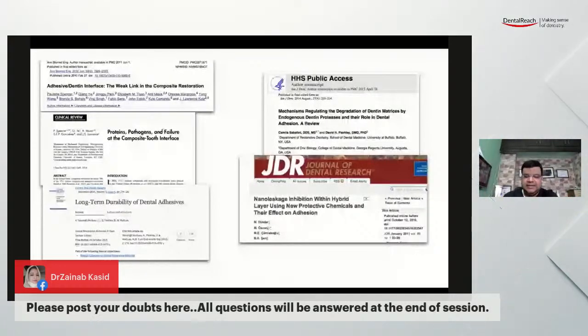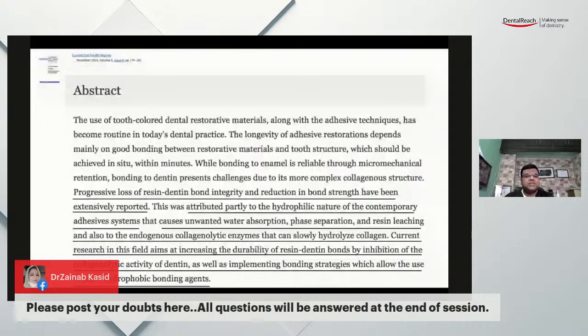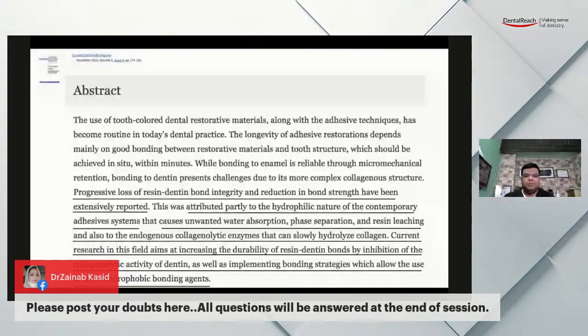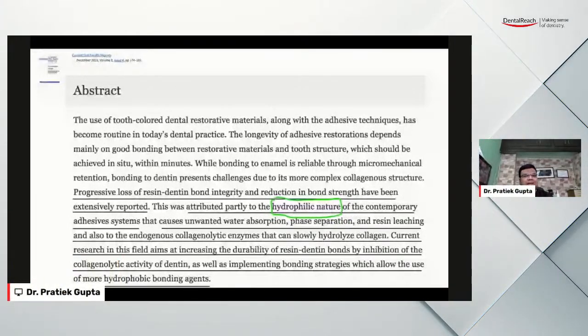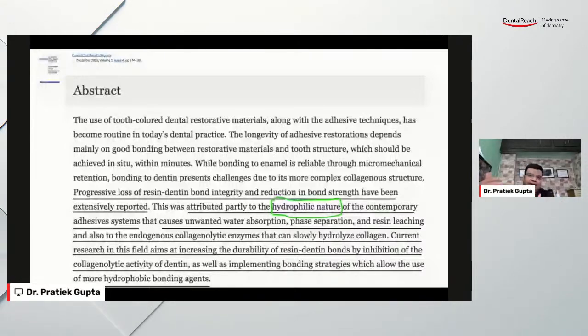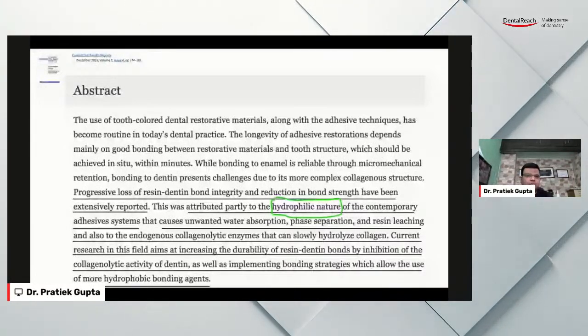It doesn't bond to the tooth, and this bonding that you are creating with the micromechanical retention doesn't last over a period of time. This was attributed to the hydrophilic nature. What does hydrophilic mean? It loves water. And what are dentinal tubules filled with? Water. So eventually, this bond, the hydrophilic and hydrophobic bond that you're trying to create with the resin... a resin is a hydrophobic material. That's why you need to dry the tooth.